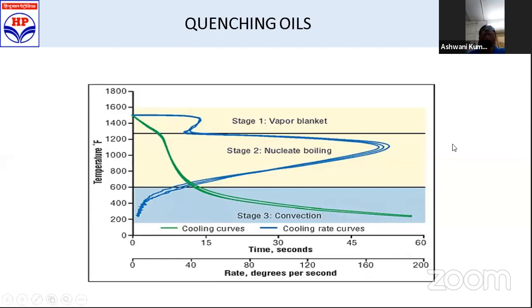Even the shop floor operator can easily put up a small graph if they are periodically checking the oil. Maybe every 3 months, 6 months, you can get the oil tested for its condition, and check that there is no moisture contamination. See, water is the enemy of oil. It emulsifies the oil and doesn't lead to the optimum performance of the quenching oil. Generally, 80 to 100 ppm we say is the discard limit. A lot of companies are offering moisture alarms today. You can install this moisture alarm in your quenching tank, so that the moment the moisture level reaches about 70 or 80 ppm, you get an alarm that you are reaching the danger zone. These can become a fire hazard as the moisture level increases. It may be a leak from a heat exchanger, or water ingress from anywhere else. So that is to be kept in mind.